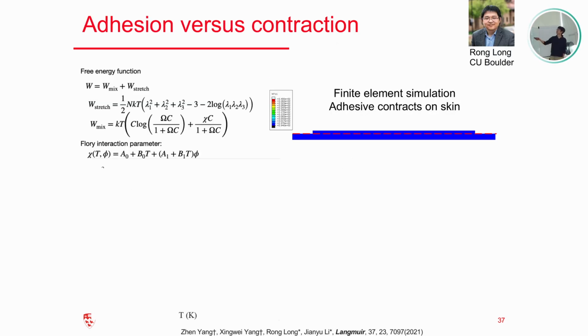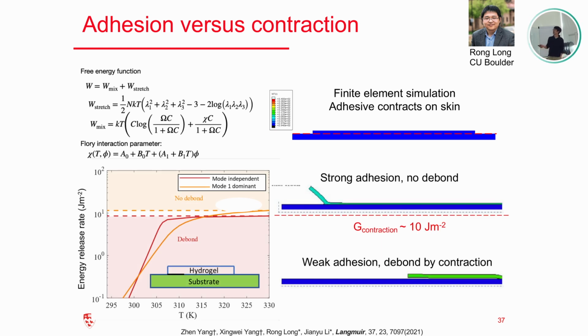And let me quickly show you there are some mechanics inside here, because you want to make sure this contraction doesn't cause delamination, right? If the adhesive contracts and gets off, that's useless. So we did some mechanical modeling to see what adhesion we need in order to let the adhesion sustain the contractions. We realized that we just need to get the adhesion over 10 joules per meter squared, and then this adhesive will remain stuck to the skin, and then they can contract